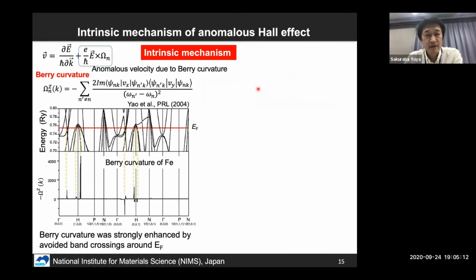So recently, researchers in the magnetics community are often interested in the intrinsic anomalous Hall effect arising from the Berry curvature of magnetic materials. The Berry curvature can be expressed by this equation. Here, the denominator is the energy difference between the occupied and unoccupied electronic bands, and the numerator is the matrix element of the carrier velocity. And from this equation, we can expect that the Berry curvature can be enhanced when two electronic bands cross around the Fermi level.